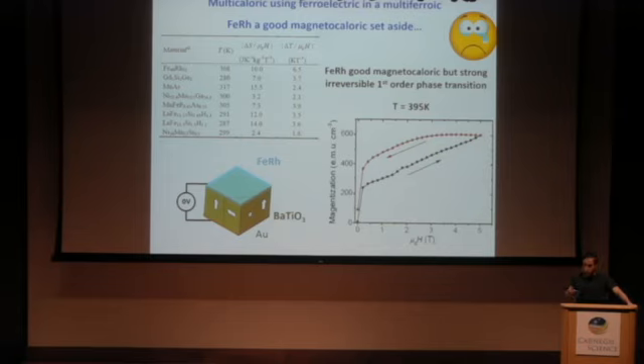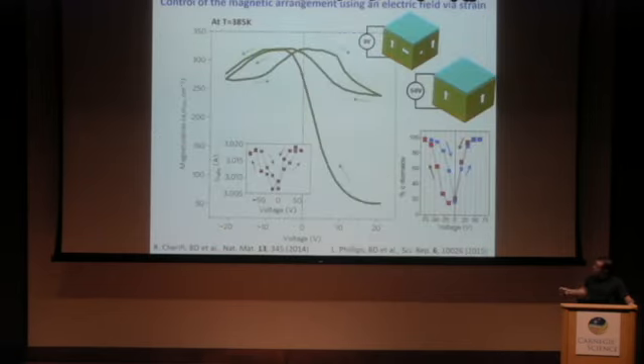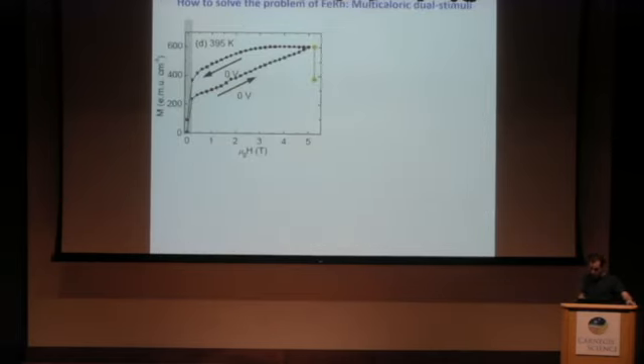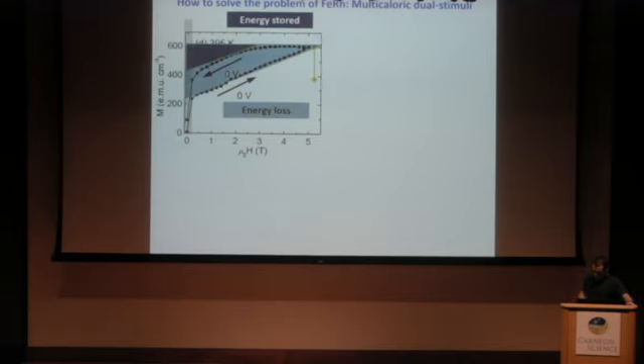One of the solutions that we propose is the following one. We take iron rhodium, we put it on barium titanate, this ferroelectric. And now why do we consider this system? Because we know that the magnetization of iron rhodium can be controlled by the voltage that we apply on barium titanate. So by playing with magnetic field and electric field, we could play on the magnetic arrangement of iron rhodium, and this is what we did actually. So we start with this one, and inside, we apply a magnetic field, and we come back, removing the magnetic field. But now the problem of this, as I told you, is that the only energy that you will extract from your system is only this triangle here.